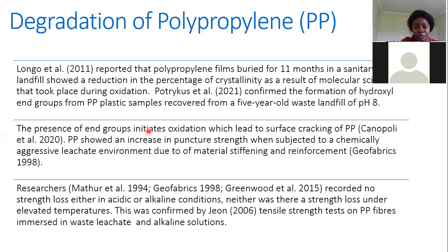However, there's one property of polypropylene that stood out. There was an increase in puncture strength when the polypropylene was subjected to chemically aggressive leachate, and this was because of material stiffening and reinforcement. But researchers showed that polypropylene recorded no strength loss, either in acidic or alkaline environments, and even in the waste leachate solutions.